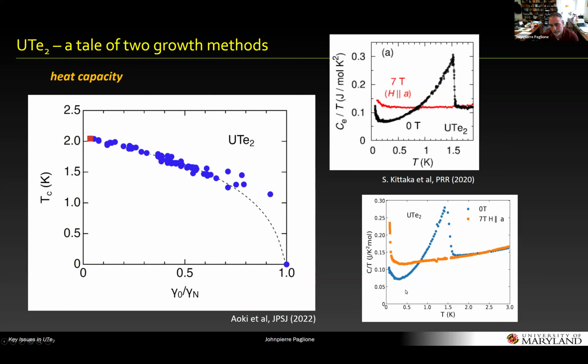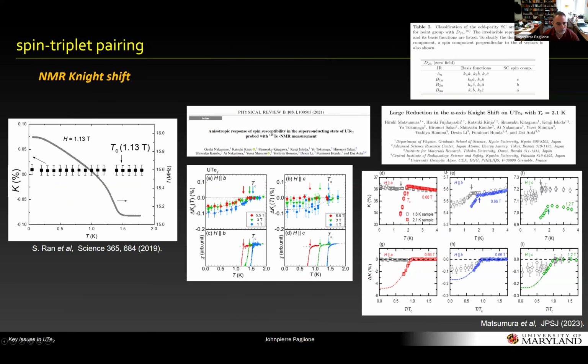And then, as I said, if you look at the lowest temperature data, you can see that there are always upturns that appear below 200 millikelvin or so, and that's also true in the highest TC samples. You just seem to have to go to a little bit lower temperatures to see it. We're trying to do a systematic study of that, but it's not easy. It requires a lot of dilution fridge time. Okay.